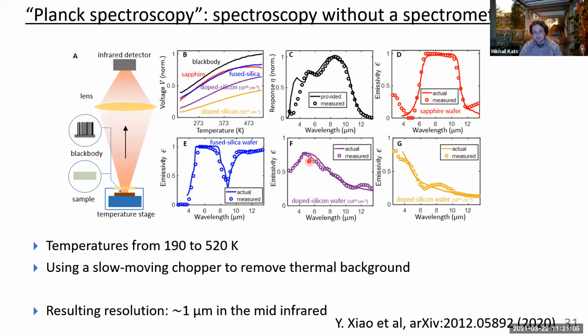And then if you take a look at the emissivity of this doped silicon wafer, where you have a plasma resonance over here, then you're able to recover that pretty well. And the same thing with the higher doping density. Roughly speaking, we have a resolution of about 1 micron in the mid-infrared, and we're able to do this, again, without any sort of prism or interferometer or anything else. It's just purely based on Planck's law. So we thought that was kind of a cool way to do spectroscopy.